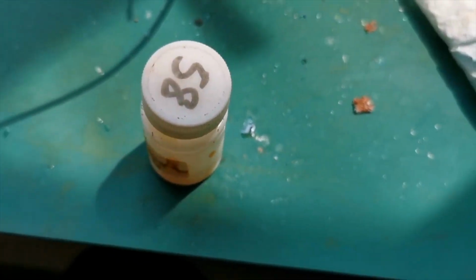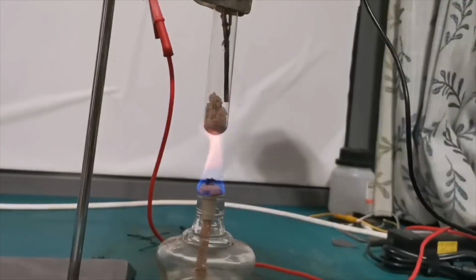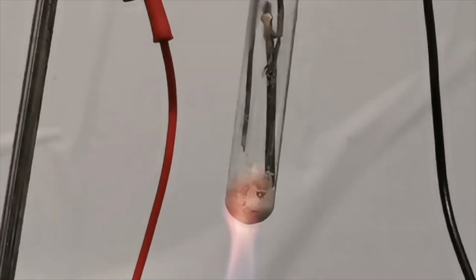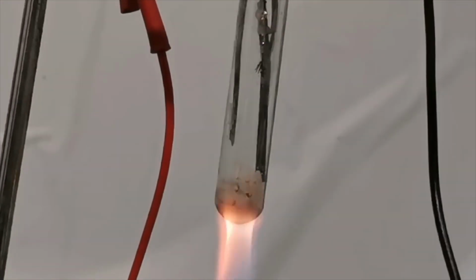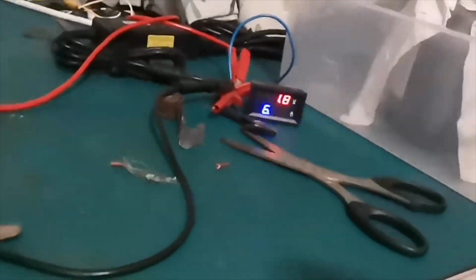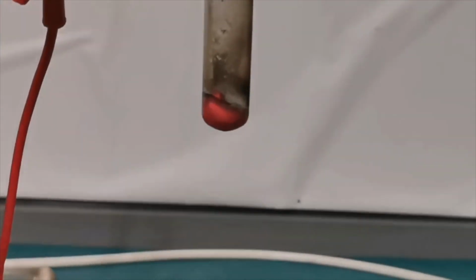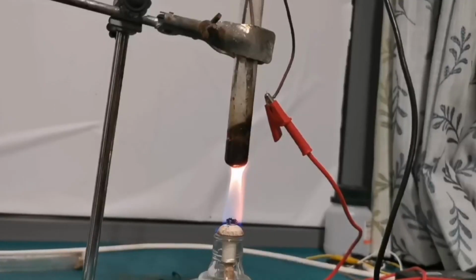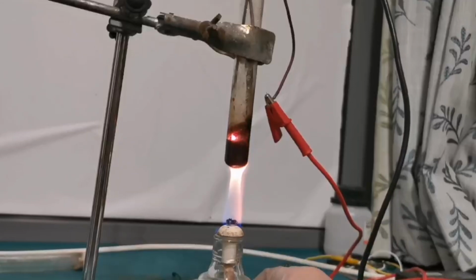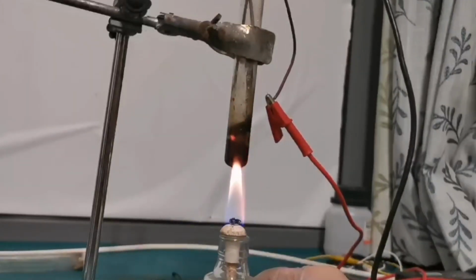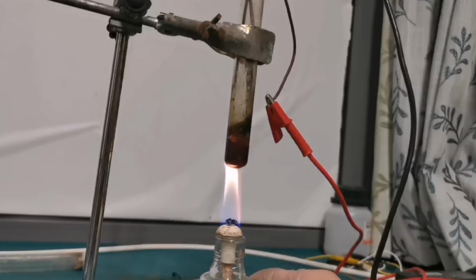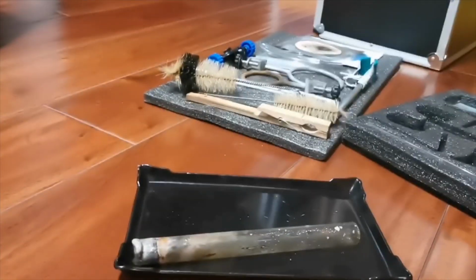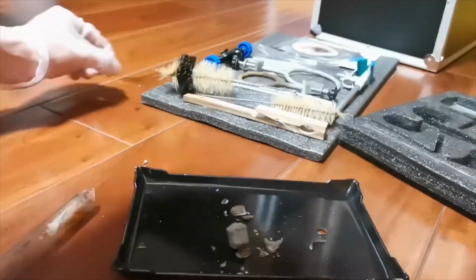it's quite pure. After the success, I then tried several other runs, but unfortunately I wasn't able to isolate any lithium. In one particular run with a test tube, the current went up to over 6 amps and kept the mixture red hot for about a minute, even when I removed the alcohol lamp from it. The lithium seems to immediately burn up in the test tube and produce some very, very bright and beautiful sparks. It was an absolutely stunning view. Still, when the test tube cooled down, I smashed it and could not find any trace of lithium metal.